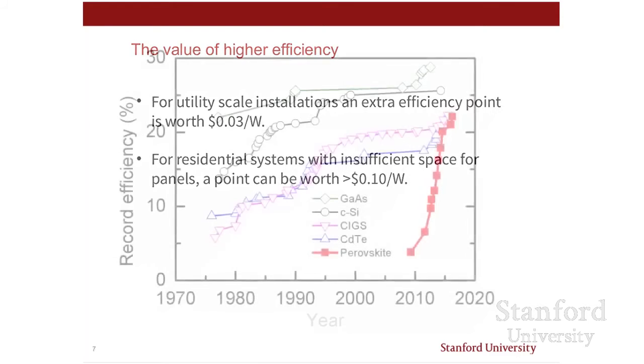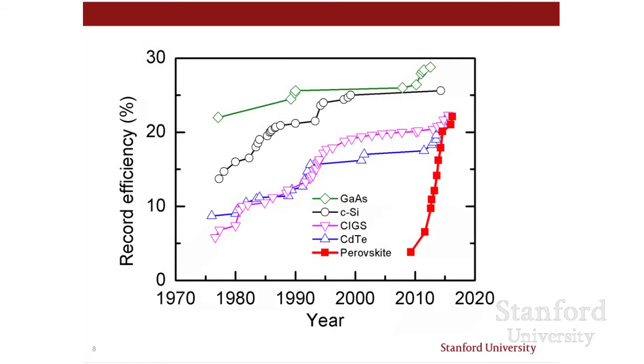And here on the next slide, we can see how the efficiency has evolved over time for some of the most important technologies. Let's start with that black curve, because that's silicon. And right now, about 90, maybe 92% of the market is crystalline silicon solar cells. And the world record efficiency is 25%, but that's for a small cell, and that's for expensive things were done to make it. The panels would be more at maybe 15 to 21%.